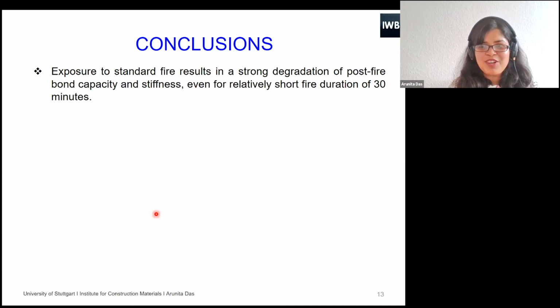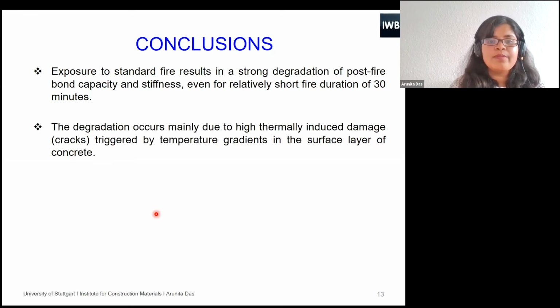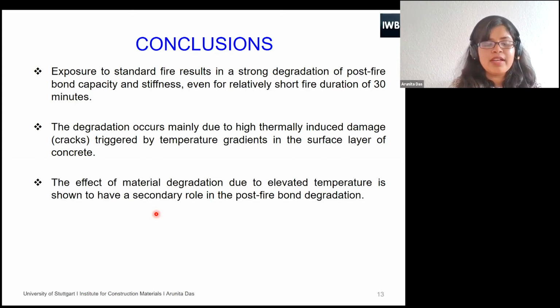So I will quickly go through the conclusion part. Exposure to standard fire results in a strong degradation of post-fire bond capacity, even for a relatively short duration of fire. This is basically due to the thermally induced damage, which is triggered by the temperature gradients. The effect of material degradation is also there, but it is not that severe. This is the basic difference between considering slow heating and considering the real fire scenario.